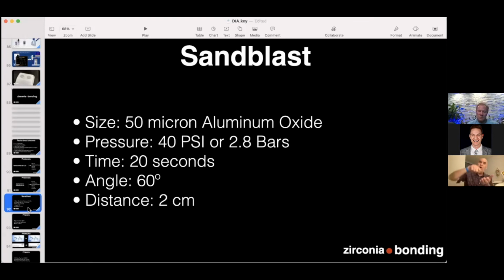Your angle, always place the nozzle of your sandblaster not perpendicular to the surface, but at an angle. Whether it's 40, 45, 55, or 60, it doesn't matter. We can control the 60 degrees. We have a device that does that in the lab. You don't need to. And you do have to keep some distance between your restoration and the tip of the nozzle of your sandblaster. All right.